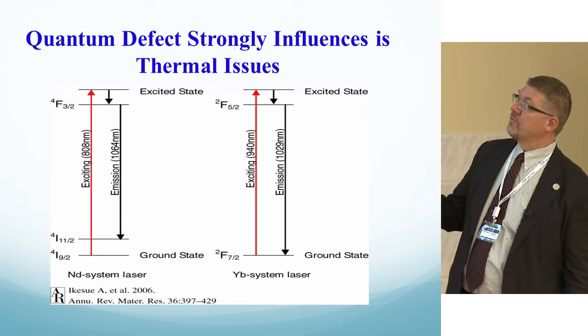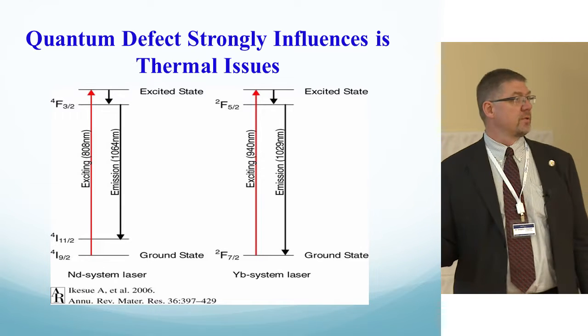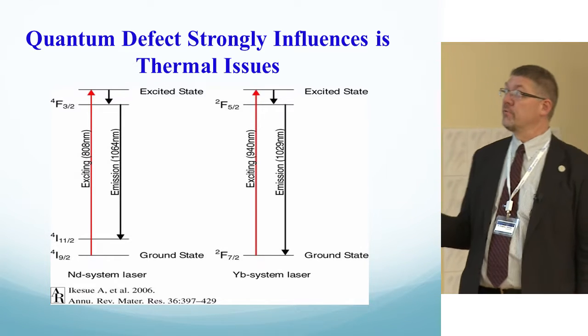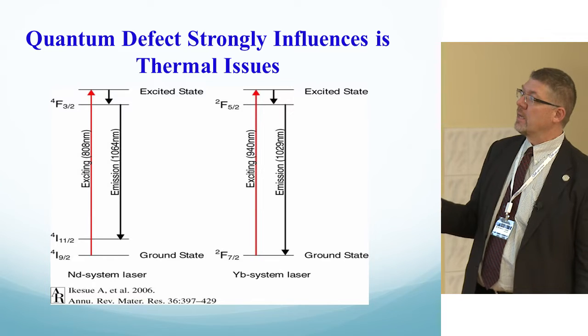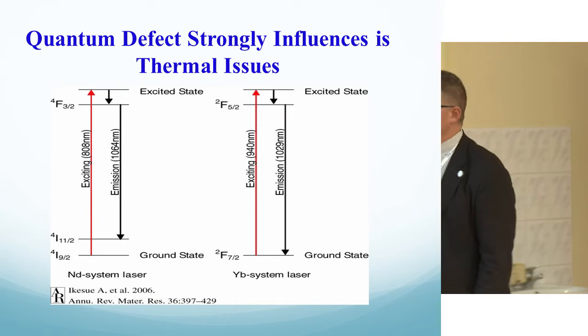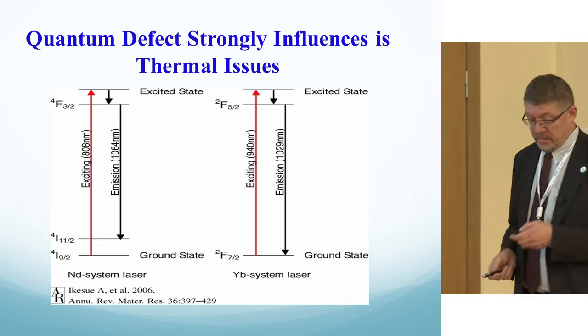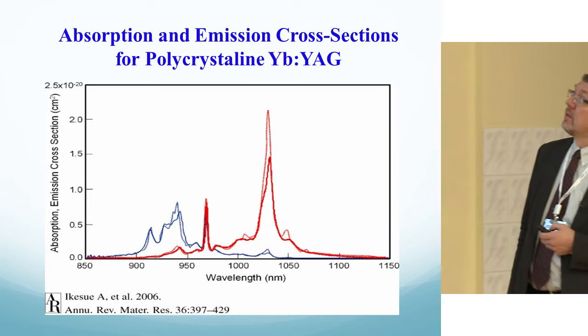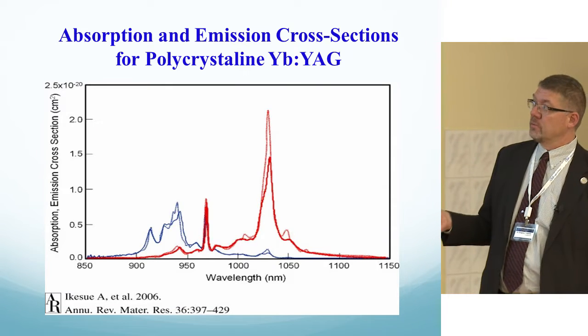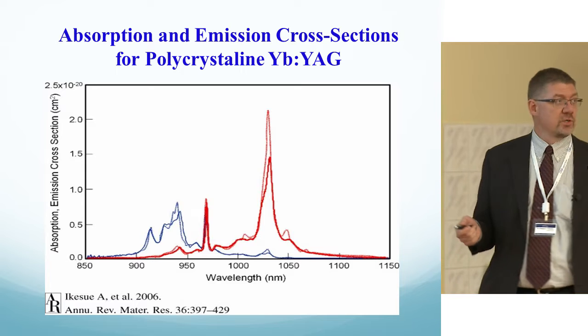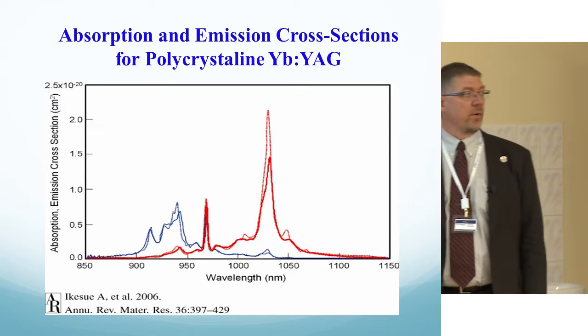And the beauty of that is this is now about an 80% efficient quantum transition. For neodymium in something like YAG, it's more on the order of 60 to 65% efficient. So this is your absorption and emission cross-section spectra for ytterbium in YAG.